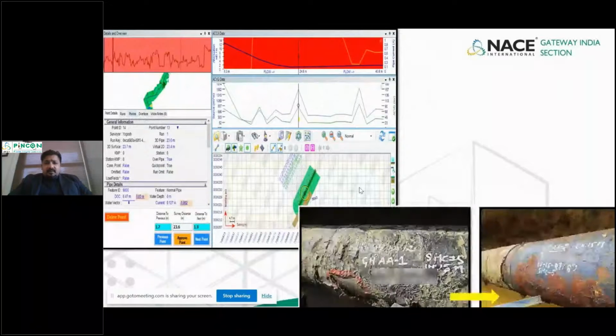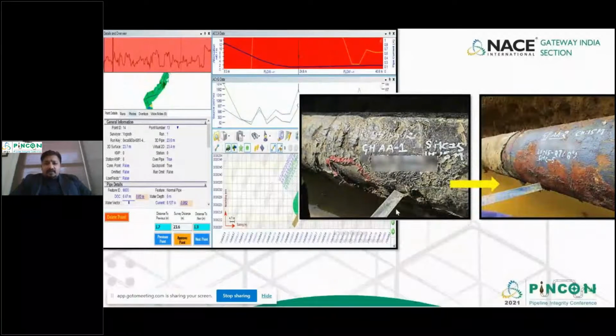This is another example. We see a coating holiday. What we're trying to show is, you see a holiday like this and you open up the coating, and then you see that the coating is moving away from the pipe, which is known as disbonding. So the coating is moving away because of disbondment, and you know why it is disbonding. It's because, based on the holiday, the area started corroding. So the deposits have caused the coating to be disbonded off from the pipe, so that the coating is just sitting on the pipe, but it's not exactly adhered to the pipe.